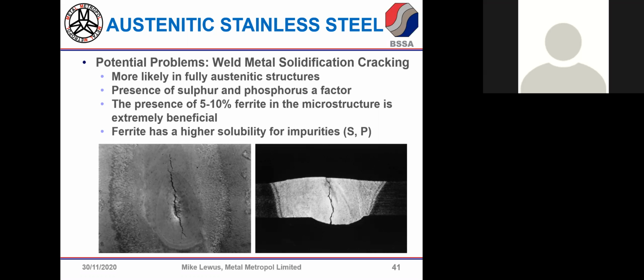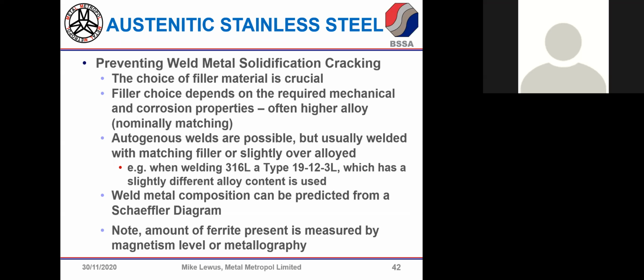If you don't have that, sometimes you can have low melting point glassy phases that combine sulfur and phosphorus, just segregating at grain boundaries, and if that happens, you just have very weak grain boundaries. So weak that just on cooling you can develop cracks in the weld seam before you've even put the material to an application. So there are things to look out for. I'm deliberately going to jump now.